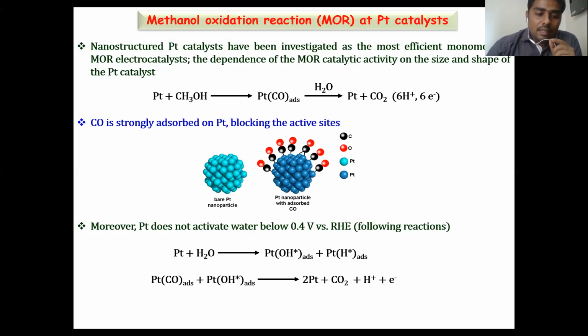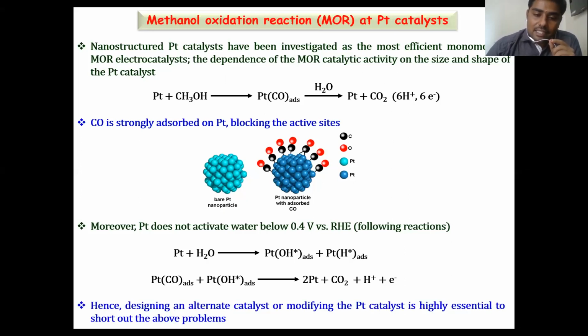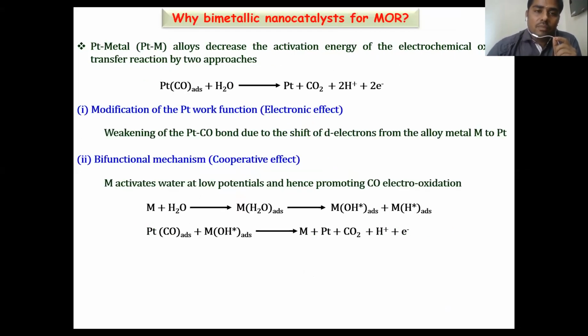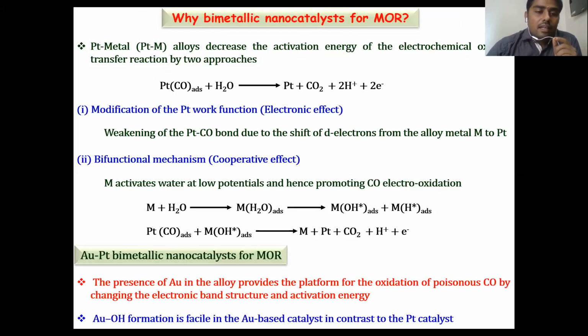Hence, designing an alternate catalyst or modifying the platinum catalyst is highly essential to sort out the above problems. Platinum metal alloys decrease the activation energy of the electrochemical oxidation reaction by two approaches. One is modification of the platinum work function, the electronic effect. In this effect, the platinum-CO bond is weakened due to the shift of d electrons from the alloy metal to platinum. The other is the bifunctional mechanism, which is a cooperative effect.